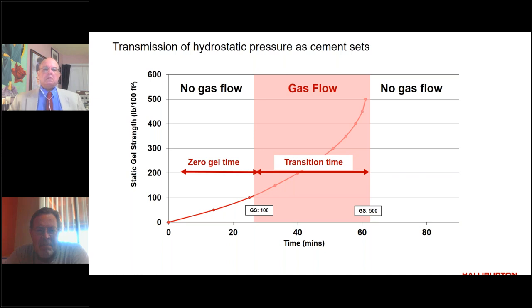The two items here, the pink or red area in the middle is the area we need to be concerned about. And we measure that in the laboratory on a machine, and we call it the time period from 100 pounds per 100 foot squared to a static gel strength of 500 pounds per 100 foot squared. And laboratory testing has shown that once it reaches 500 pounds per 100 foot squared, it's considered solid. Nothing will flow through it at that point in time.